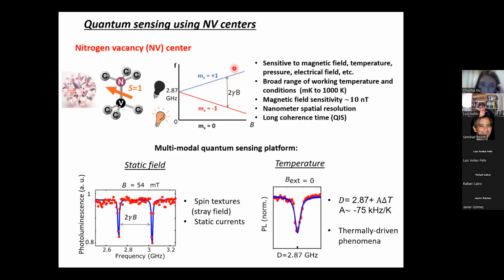So during our experiment, we can monitor the photoluminescence generated from the NV center as a function of microwave frequency. When the frequency matches the NV electron spin resonance frequency, the NV spin will flip from 0 to one of the other spin states, and this leads to a decrease of the photoluminescence. And from the separation of the -1 and +1 states, we can read out the static field at the NV location. So we can use this method to image the stray field generated from the spin texture of the quantum material, or the Oersted field generated from the current in the material.